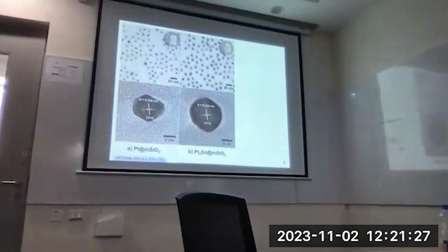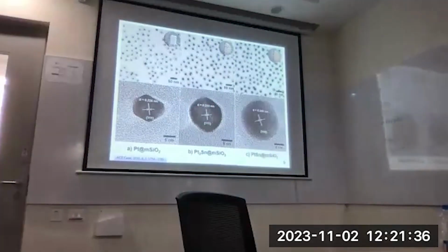So yeah, this is starting with this platinum, and then when you add the tin and you grow it under those solvothermal conditions, right? You grow it and then you make this platinum 3 tin in this case. Then you have platinum. All the scale bars are the same, but when you add more tin, the tin will selectively reduce only on the surface of the platinum and form this larger particle. And the silica shell acts as the reactor to grow these things. Right?